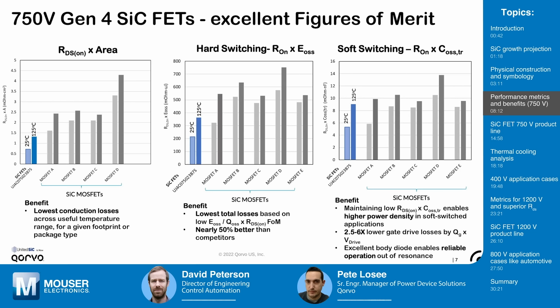And then you can combine this with typically a lower gate charge and the fact that I said you can drive from, let's say, 0 to 12 volts. In some of these soft switching circuits, like I said, the cascode FET may be fully enhanced at 10 volts. So now you can really cut down on your driver losses because you can drive at a lower voltage swing and feeding a lower QG. And that excellent body diode, which has a very low recovery charge and a low VF, will allow you to operate potentially even outside of resonance in soft switch converters.